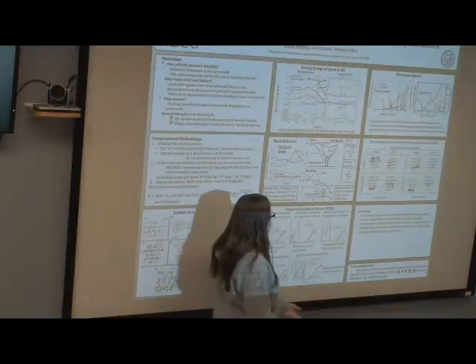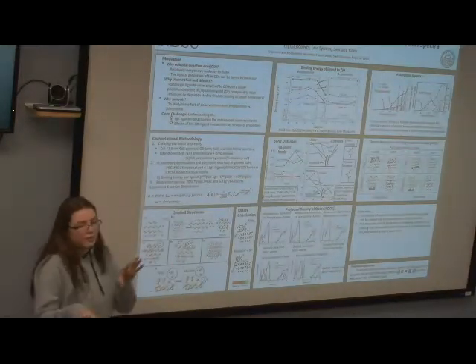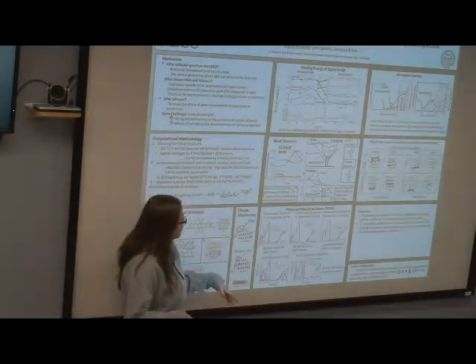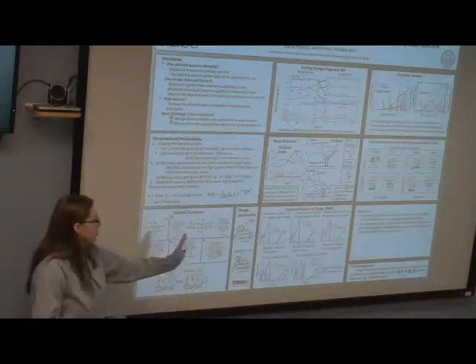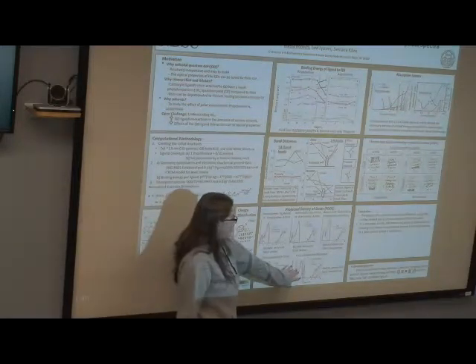And then this last one is just showing the difference between no amine and propylamine and no amine and acetonitrile, just emphasizing that it's necessary to have amine in propylamine, but not in acetonitrile, in order to not create trap states. And then down here we have the fully passivated bithiol and fully passivated bithiolate.